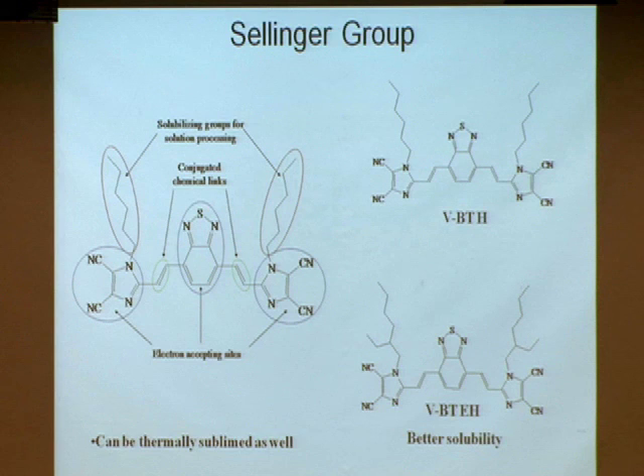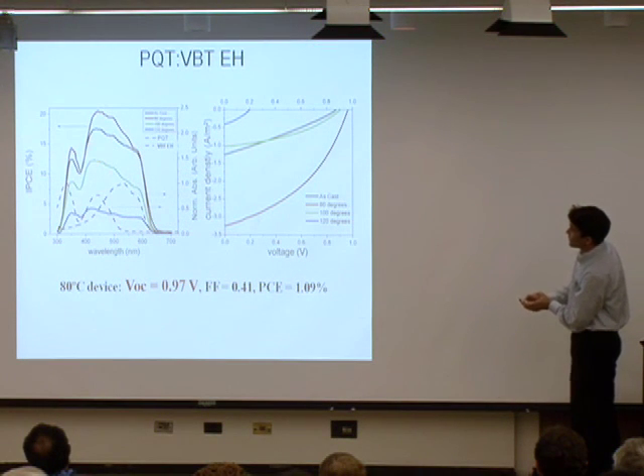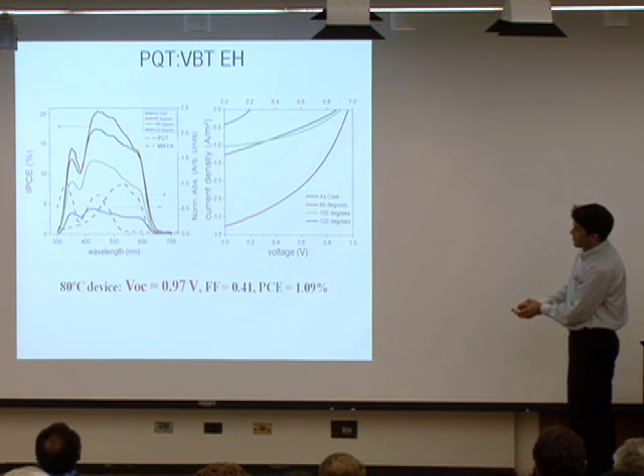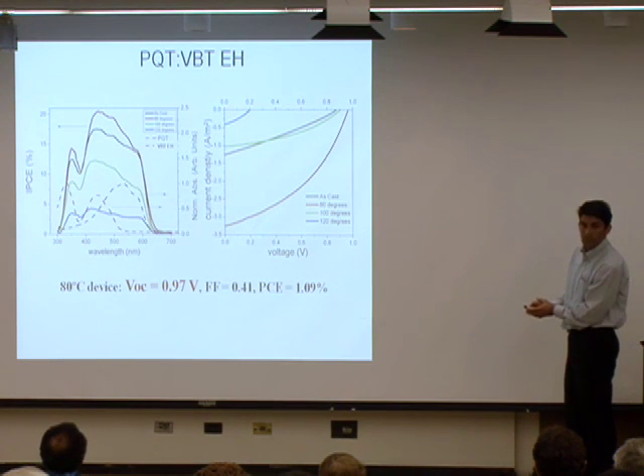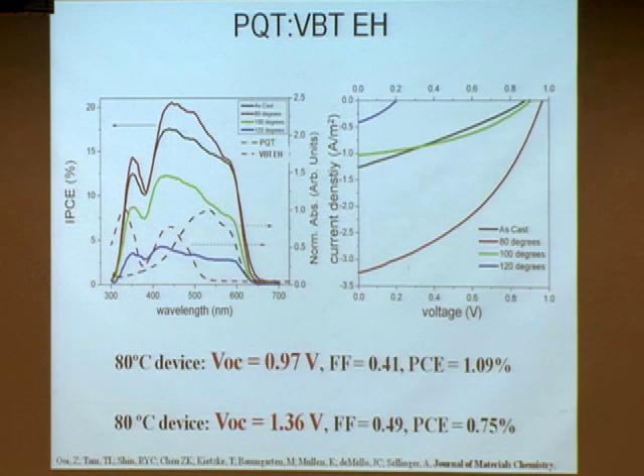So now we go ahead and make solar cells. We combine these new acceptor materials with a known donor polymer that we can simply buy. We make devices, and one of the things that we're targeting is open circuit voltage. In this case, we can improve open circuit voltages over some of the more traditional materials matching, which are usually in the 0.6 to 0.7 range. And then we can further extend this type of VOC just by selecting another type of donor material. So this is basically a way that we can tune open circuit voltage, and now we're looking at a lot of the issues like Mike was mentioning, morphology and other things, to optimize this even further.